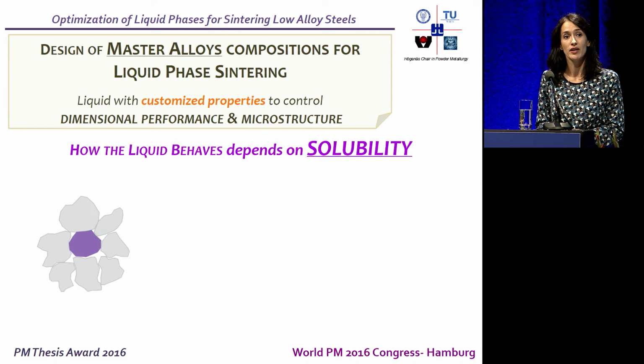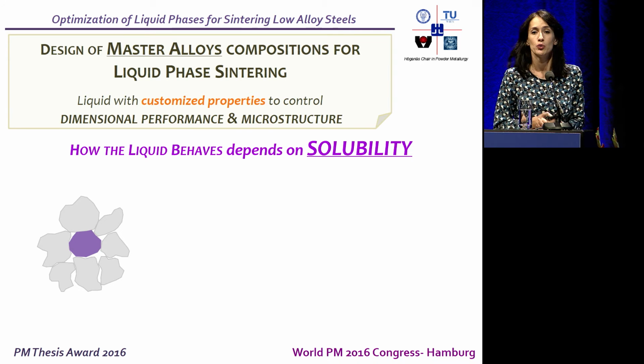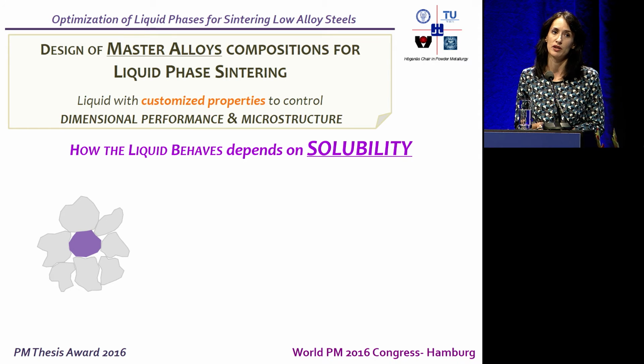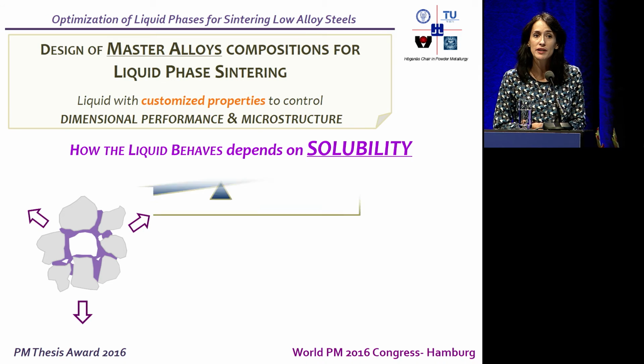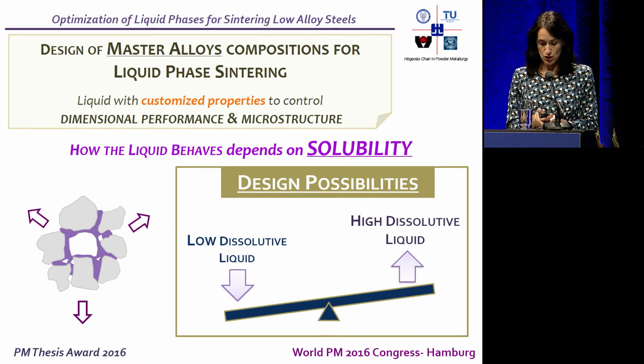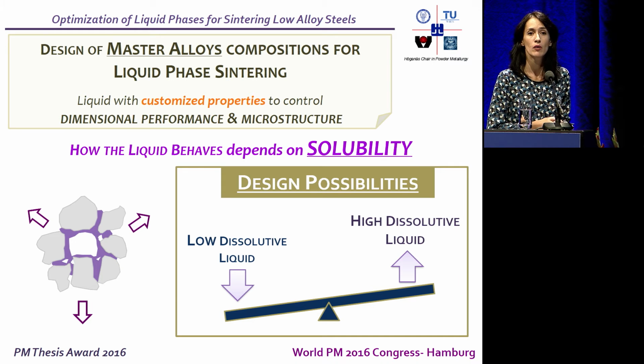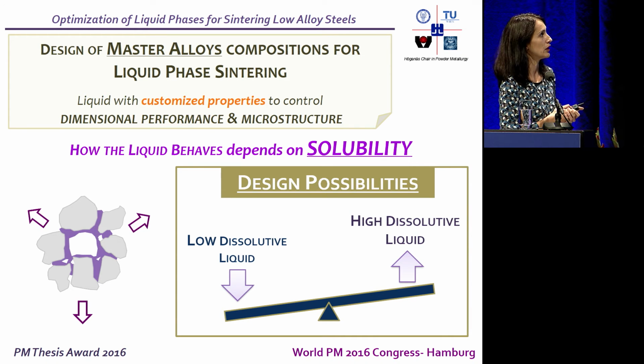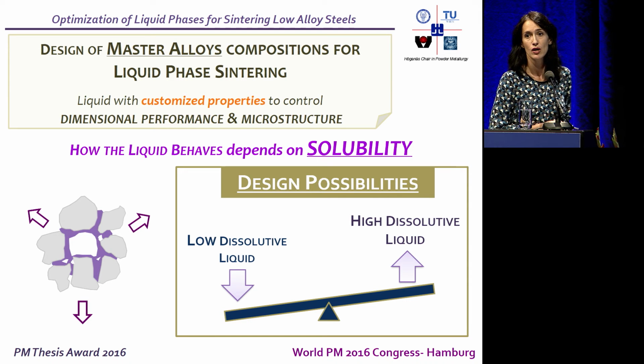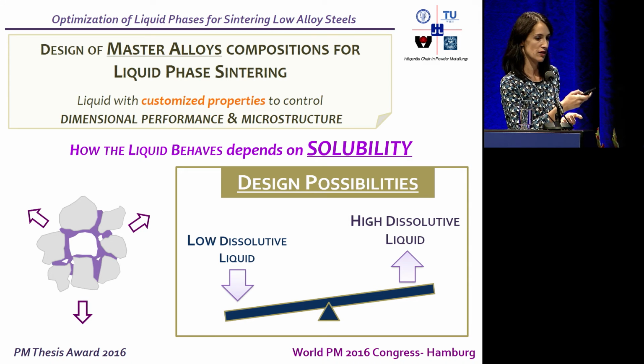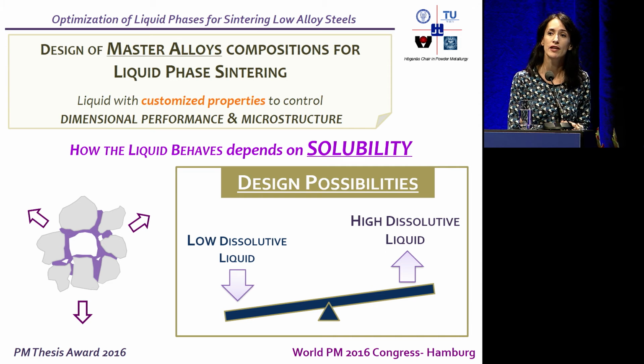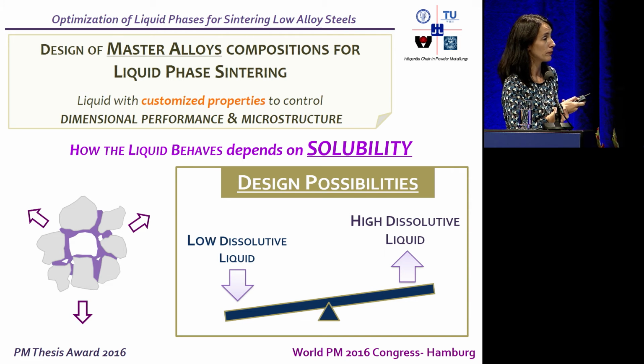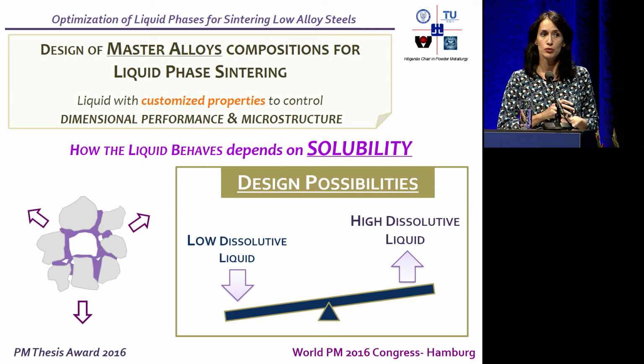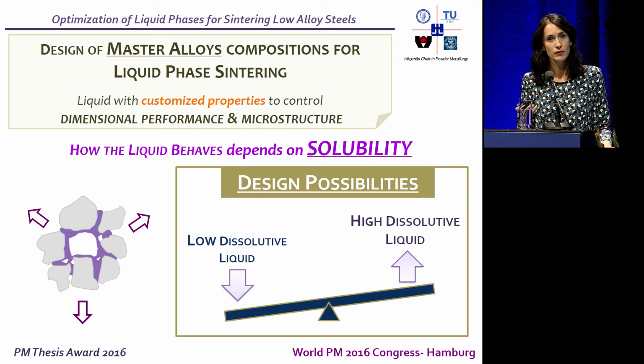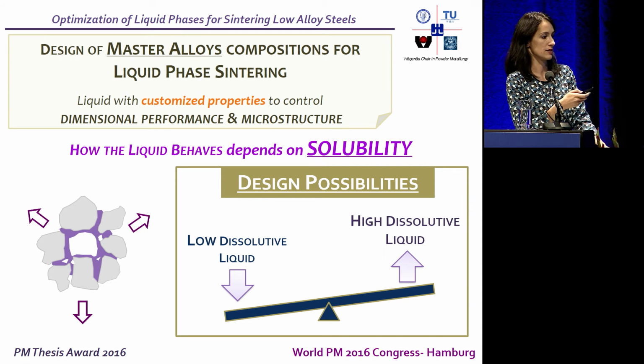And we can say that we can do it if we pay attention to the solubility relation between the liquid and the solid phase. So based on this solubility, we have two design possibilities. We can have a low dissolutive liquid, which has infiltrating properties, so the liquid creates and rapidly penetrates through the contacts. But also, we can have, on the other hand, high dissolutive liquids with non-infiltrating properties. So this means that the liquid will be created, but will not be able to penetrate and distribute. Let's see which consequences this has.